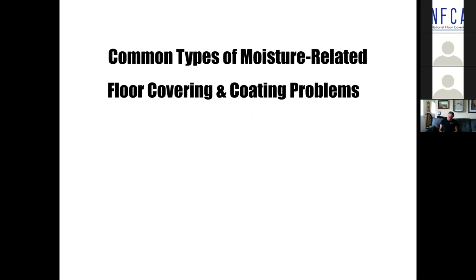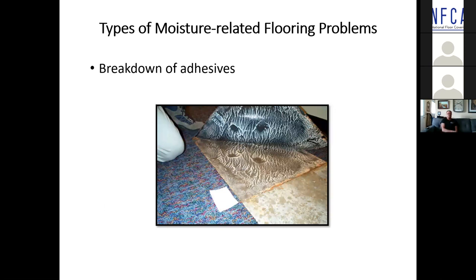Since we're doing this as a flooring organization, let's take a look at some of the common types of moisture-related floor covering and floor coating issues. The breakdown of adhesives. Okay, this is a job I did out in Oklahoma. We already talked about it not necessarily being, if you will, re-emulsification, but there was enough moisture in this concrete to place the soluble alkalis, which are always present in the surface region of the slab, into solution, and they're always present in the surface region at a greater concentration than they are deeper in the concrete.